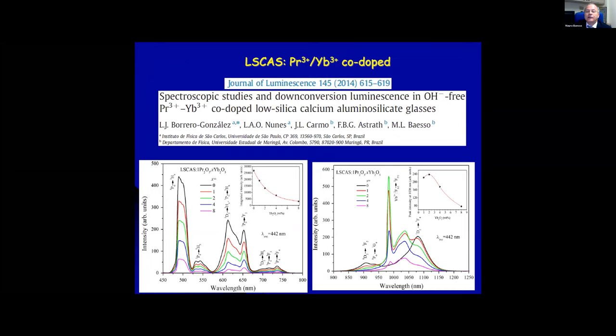Second, we also have an example which didn't work, when you try to use praseodymium as a sensitizer to transfer energy to ytterbium. In this case, we saw a lot of back energy transfer, and it means here you see there is no efficiency. So praseodymium is not a good system to be used in this glass.